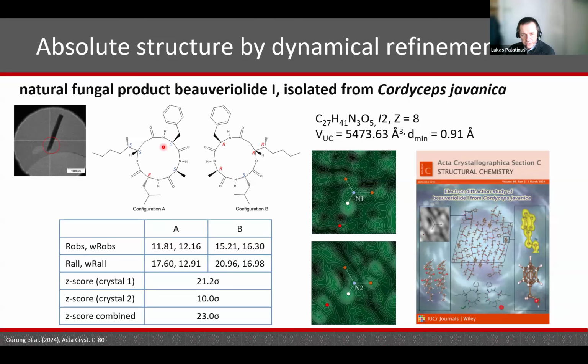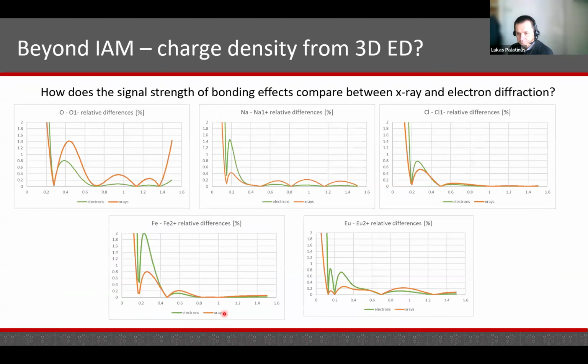It's a cyclopeptide which has mostly S centers of the chiral carbons on the cycle, but one of them is R. And in this case, even though the molecule is relatively complex and the data were not of super great quality, it turned out that, again, the absolute structure can be determined very easily. The statistical significance in this case, the combined reliability, was 23 sigma, which is an extremely high value, so extremely high reliability.